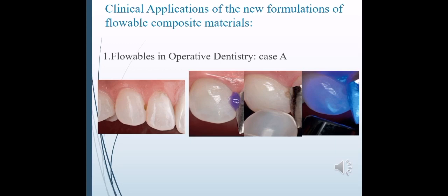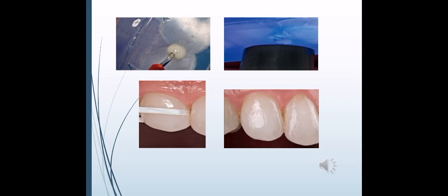then the preparation area was etched for 15 seconds with phosphoric acid, and an adhesive bonding agent was placed over the surface and allowed to dwell for 10 seconds, dried for 5 seconds, and light cured for 10 seconds. Then a clear siloxane matrix was placed over the maxillary arch, and an opaque A1 shaded flowable resin composite, Genial Universal Flow, was injected into the preparation through a small opening and light cured through the clear matrix. Then the interproximal zone was inspected with unwaxed dental floss, and as we can see in the last picture, the completed class 3 composite restoration.